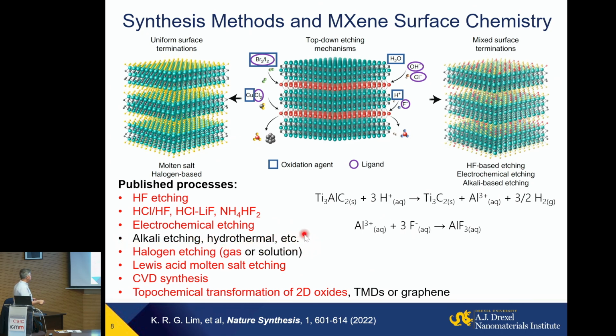Alkaline, hydrothermal, supercritical CO2. But what is also emerging in recent years is etching that produces halogens. First of all, Lewis acid molten salt, but also gaseous etching using chlorine, HCl, others. You can also do it in solution. In this case, you can actually get uniform halogen-terminated MXenes. And they have different properties because their surface is different.